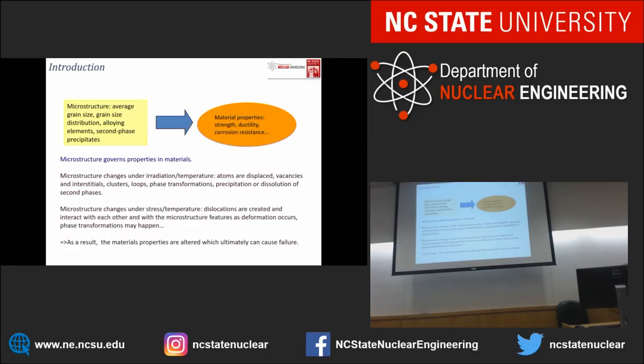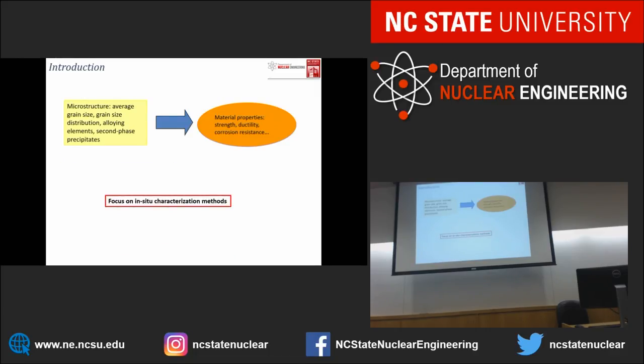For example, irradiation can induce point defects in the materials in the forms of interstitials and vacancies. These point defects can diffuse within the materials and result in the formation of dislocations, precipitation, and segregations. So at the microscopic level, this microstructure change induces an increase of the yield strength, which is known as the radiation hardening. So we want to find a relationship between the microstructure change and the influence on the material properties. To achieve that, we use in situ characterization methods.